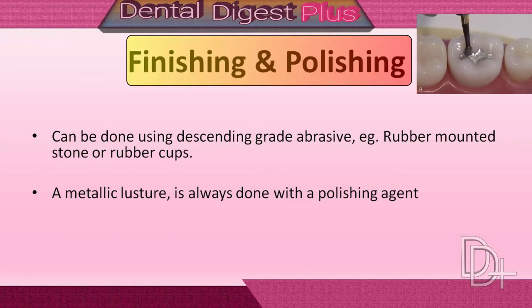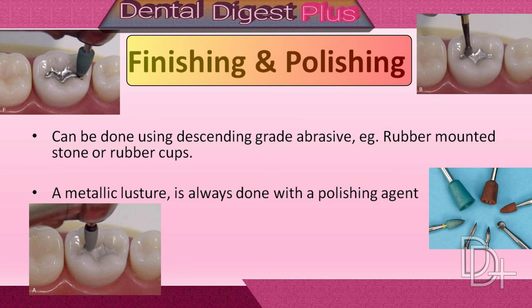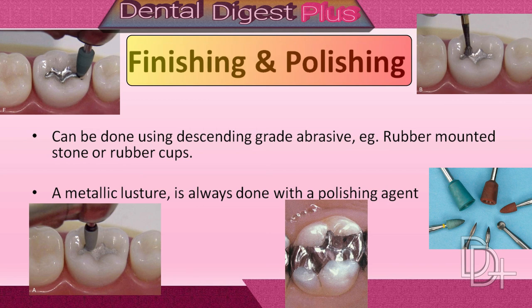Finishing and Polishing. Finishing is the process which continues the carving objectives, removes flash and overhangs, and corrects minimal enamel underhangs. It should be carried out 24 hours after amalgam insertion. It provides better aesthetics and allows prolonged service with minimal corrosion. Polishing is the process which creates a corrosion-resistant layer by removing scratches and irregularities from the surface. Polishing agents used are precipitated chalk, tin, or zinc oxide.